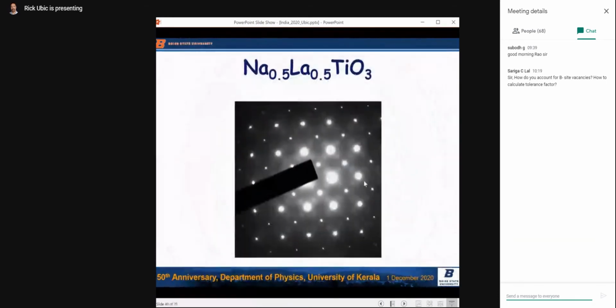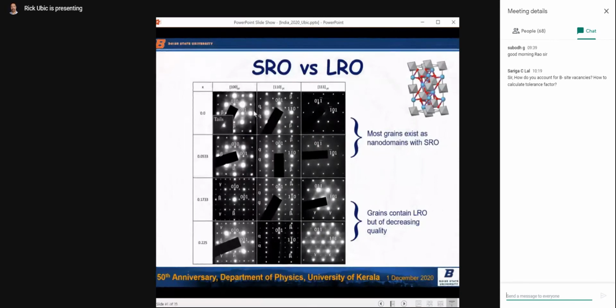If you look in electron diffraction, aha, there's the ordering, right? All these diffuse spots are ordering, but they're short-range ordering. You have nanodomains of ordering now, right? So you have good ordering, but on a very small scale. So the summary here is that at low X values, you have most grains with order, but they're nanodomains. So it's a very short range, a good short range order, so the diffuse spots. And as you go up in X, you deviate from the perfect ordered composition. So the degree of ordering decreases, but the extent of ordering increases. You get long range order now, but just of worse quality. So you get more discrete spots, but they're still weak. So that's what's going on.